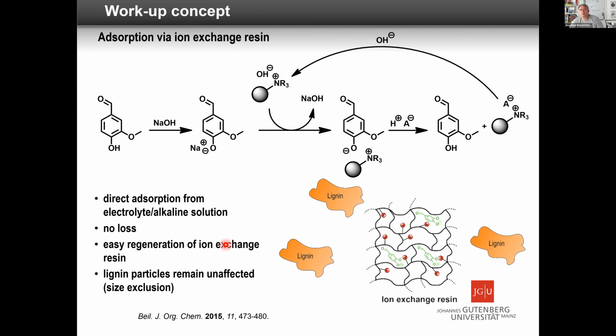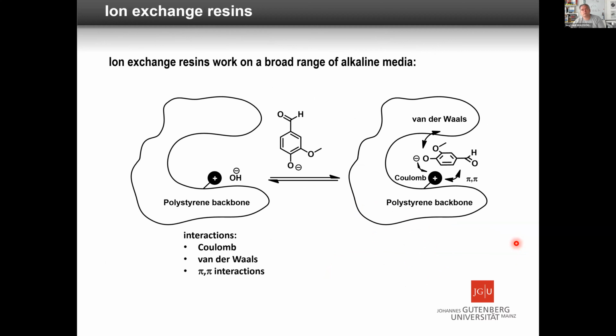And this is a very important point. The lignin particles keep off of the gel type resin, and you just put the small or low molecular weight system in that, and the other ones which are not used could be electrolyzed further or brought back, and the black liquor directly into the mill once more, and the inorganic chemicals are not disturbed. Why does it work even at high alkaline conditions? Well, you have a backbone interaction, and when the molarity of the black liquor becomes higher in caustic soda, then the interactions become stronger, and therefore it works on a really broad range of alkaline media.